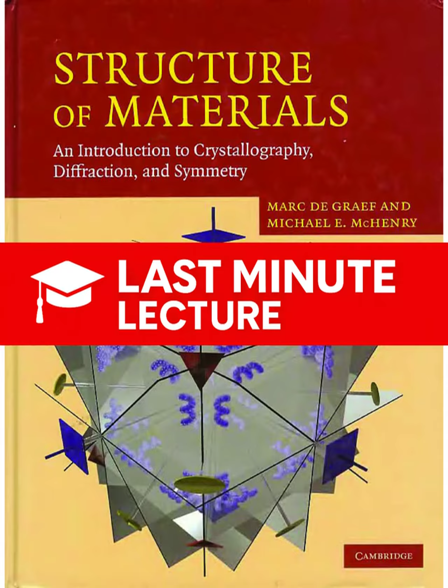So we need that transformation matrix, alpha, to define the relationship between the old FCC basis vectors and the new primitive ones. And we can find that matrix just by visual inspection. The primitive vectors in the FCC system run along the face diagonals. For example, the first new vector is half of the original A1 plus half of the original A2. That observation defines the transformation matrix, which will be full of fractions like 1/2.